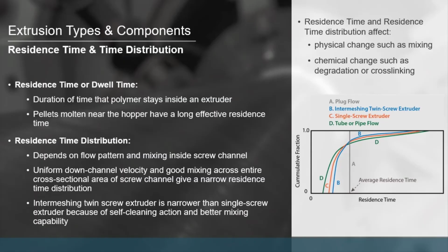Residence time or dwell time, as we talked about, will significantly impact things, especially if you have temperature sensitive materials. So care should be taken in dealing with such materials. One simple example is bio-based plastics, polylactic acid. If you are dealing with this kind of material system, they have very narrow processing ranges. Let us say, for polylactic acid, it's actually 180 to 190, right? In fact, 160, or 167, is its melting temperature, so up to 180 is fine. Anywhere between 160 to 180 is basically what you're looking for.